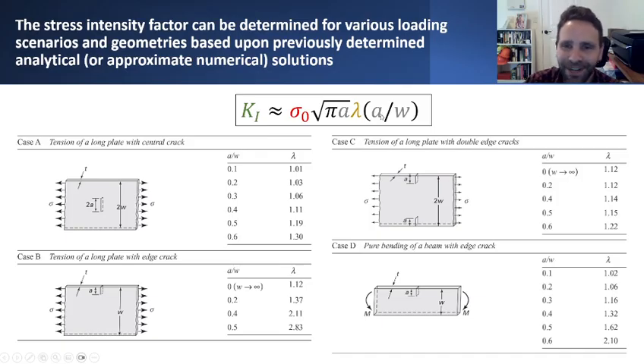So there's some extra modifications we have to do, but it really just looks like this. It maybe adds some extra geometry correction factor that depends on various conditions like the type of loading and other things like the dimension of the plate or the relative dimensions of the crack compared to the width of the plate. So all of that taken into account, we can then just say, well, for this particular plate geometry and this particular crack size to plate width ratio, I can then plug these values in and directly figure out what is the stress intensity factor for a given plate geometry and a particular loading scenario.